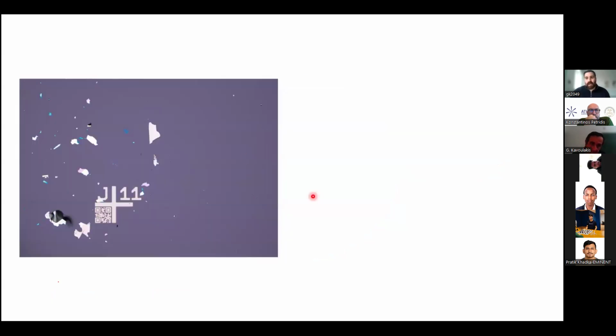So here comes the first part of our experimental approach. To deal with that, what we do is this. We will do the exfoliation and select the flakes that we are interested in, and we will characterize them initially with several spectroscopic techniques like Raman spectroscopy, photoluminescence, reflectance, second harmonic generation, whatever gives us details about the thickness, about the origin, about the uniformity, everything. Then we develop code, and this code scans the chipset and automatically identifies the flake that we look for. And on top of that, it doesn't just say where the flake is. You see that I have the coordinates, given that my system will also read the marker and the QR code, and it will give me the exact coordinates of the position of the flake.